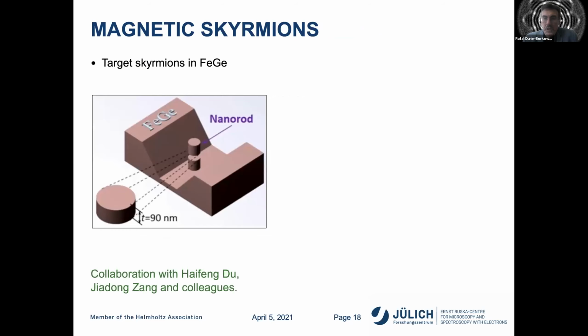So in the first example, instead of a magnetic stripe, we used focused ion beam milling. This is a cooperation with Haifeng Du and Jiadong Zang and colleagues to make a little cylindrical structure rather than a stripe. And if we image that cylindrical structure along its axis, then magnetically we see a skyrmion in the middle, and then the edge twist now forms a magnetic state around the edge which spins in the opposite direction. This little cylinder has a diameter of about 150 nanometers and a thickness of about 100 nanometers.